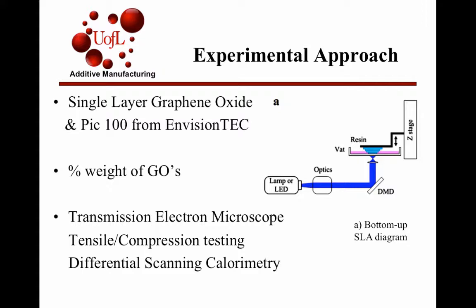There are 3 ways to prepare graphene oxide in a polymer. There's in situ, which is basically where you combine the graphene molecules with the polymer, and then you insert some kind of reactant that combines and allows the structures to react in situ while you're printing and form the structure. The second is liquid preparation, and then there's also melt preparation.